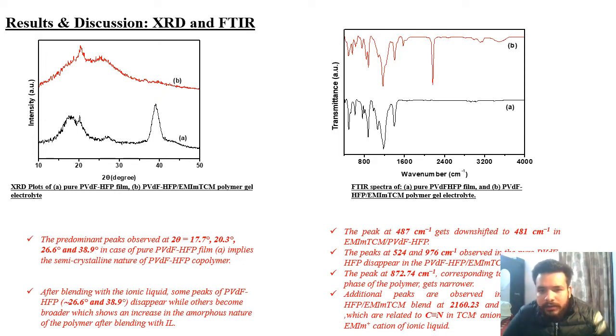There are also some additional peaks in the ionic liquid doped PVDF-HFP film, at 2160.23, 3000 and 3156 cm^-1, which are due to the anion and cation of the ionic liquid. So this FTIR data shows that ionic liquid is perfectly blended with the copolymer PVDF-HFP.